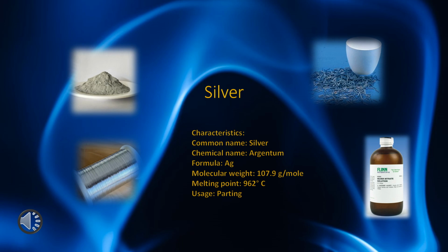Even though the silver is considered to be pure, there may be some gold alloyed with the silver. Gold and silver appear to be married to each other. For any parting process, there must be an adequate silver to gold ratio. Anything less than 4:1 will result in an inefficient parting. Adding silver also aids in the reducing of the gold loss. All this will be covered in future presentations.